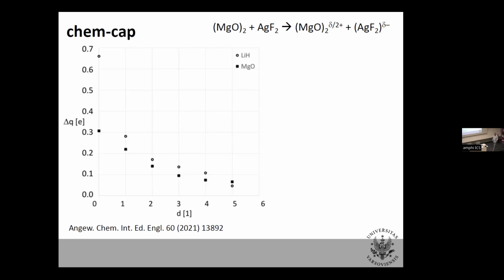So think about this as a sort of experiment when you have two insulators, thin layers, and you bring them closer and closer, and you do just nothing, and they become metallic. It is not chemical doping, right? I didn't alter stoichiometry whatsoever. And yet, they dope each other. Looks like a miracle, but I assure you it's not. Okay, so you can in fact write the equation of the reaction here, and this will not be the equation that kids put at school, iron 3, iron 2, because there is this delta here, which is non-integer. That's why there are no such equations in chemistry textbooks.